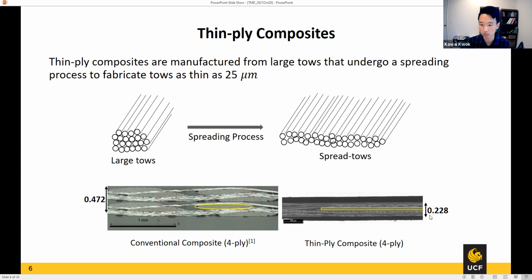But in a thin ply composite, it's really thin. The same amount of fibers are now being stretched out, and so it becomes really flat. The idea is that you can really compress the thickness of that final composite. And again, the idea is to use that small thickness to achieve high flexible curvature.